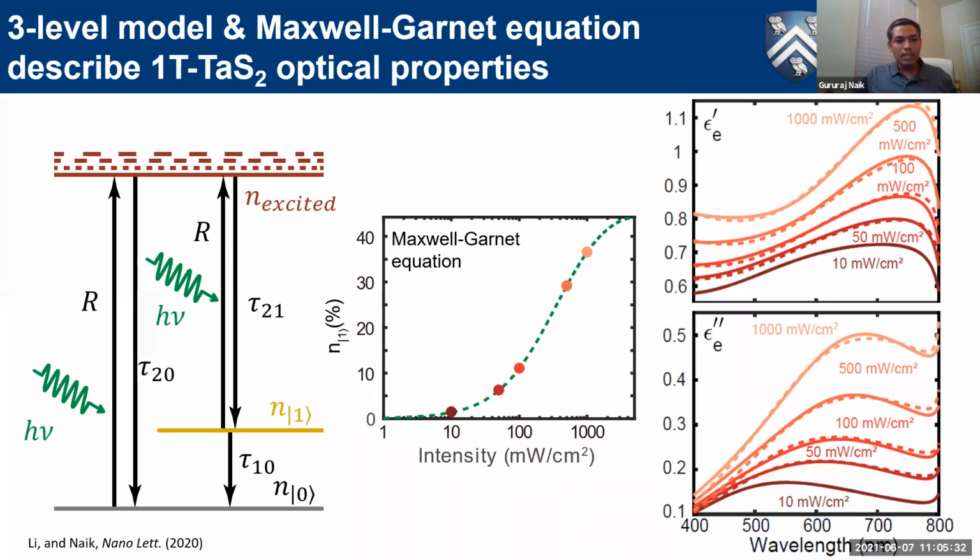But now we know that those happen because, depending on what you cover or encapsulate this material with, the Coulomb interaction between all these different domains can be very different. Their energy changes. And because of that, the energy difference between different stackings completely changes. That's why the tunability, or even suppression of charge order or emergence of superconductivity, must now be varying in the samples. And that's actually what motivated us to look at the possibility of light-induced superconductivity.